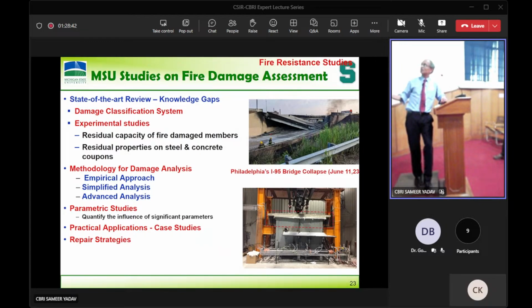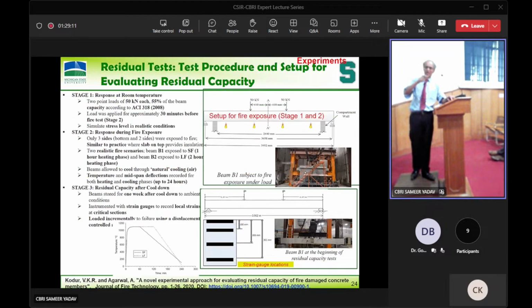So what did we do? First, we looked at the state of the art, as I already showed you, and identified the knowledge gaps. Then we came up with a classification system for damage assessment, right? Then we did a lot of experiments, and then we developed methodology at different levels, depending on the different extent of damage, which have different classes of damage. Okay, and then we did some practical applications and repair strategies. So first of all, let me quickly show you some experimental studies.